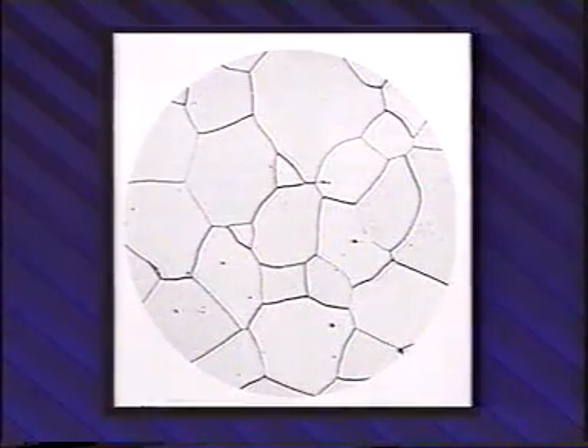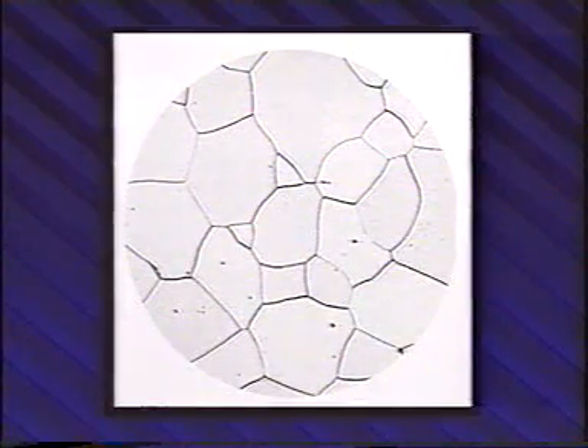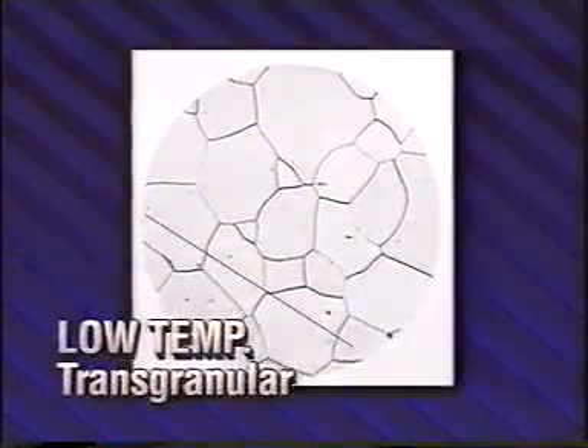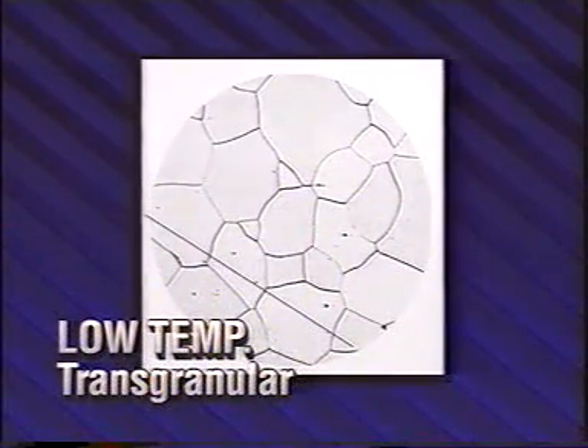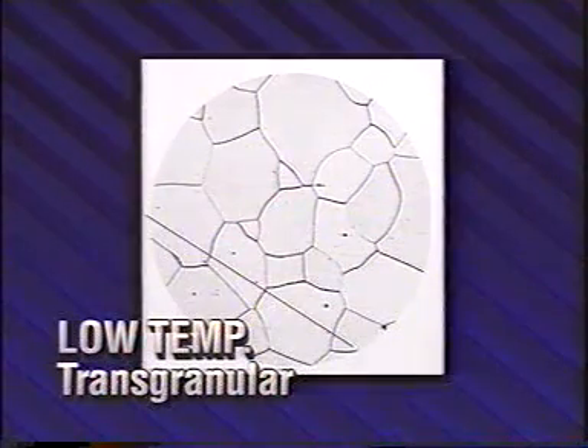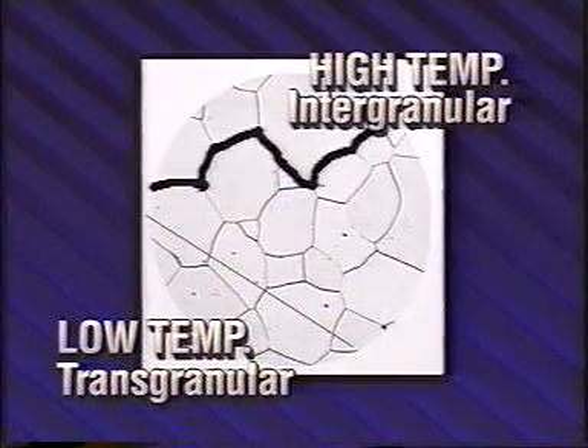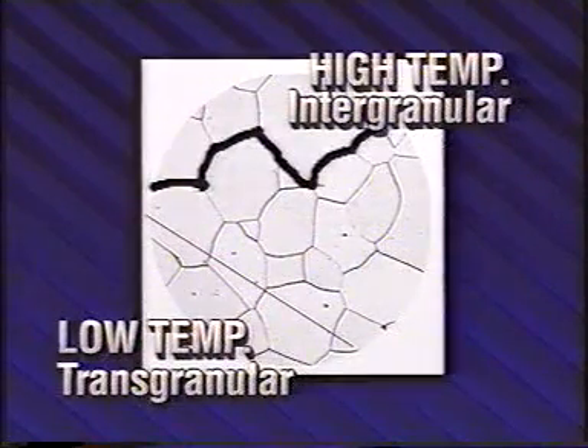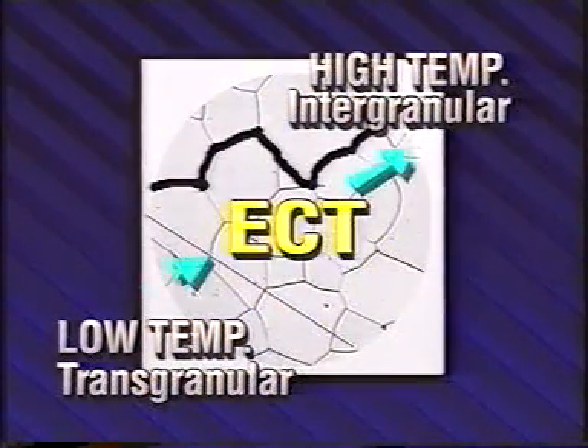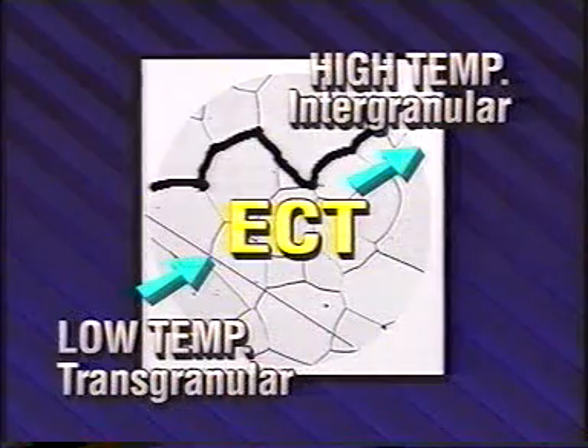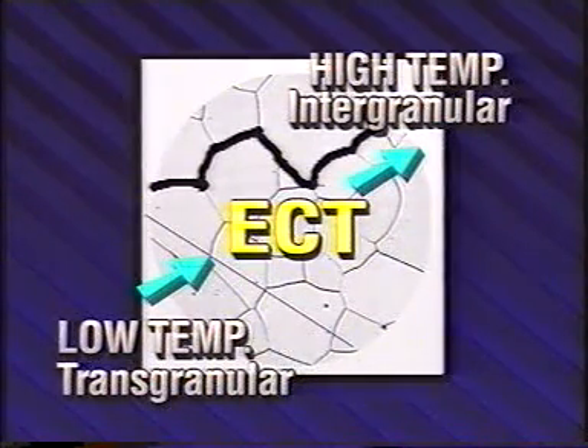The transition from transgranular fracture to intergranular fracture occurs because the properties of grain boundary regions differ from those of grains. At low temperatures, the grain boundary regions are stronger than grains. Therefore, deformation and fracture are transgranular. At higher temperatures, the grain boundaries are weaker than grains, so deformation and fracture are largely intergranular. The transition from transgranular to intergranular fracture occurs at the equicohesive temperature.